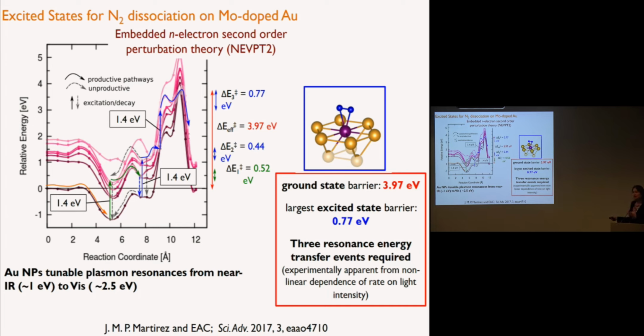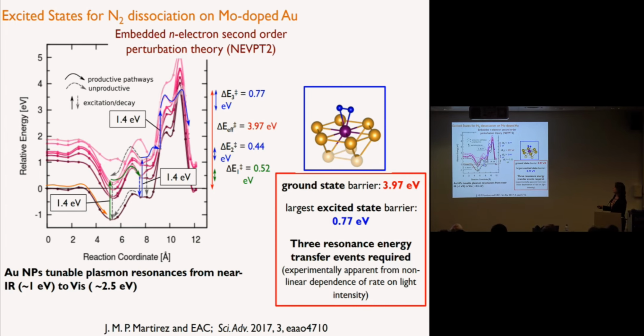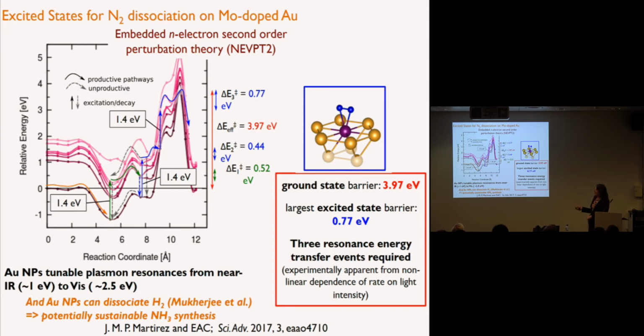And what our calculations, looking at these oscillator strengths, tell us, and the fact that we don't see charge transfer, is that this is happening through resonance energy transfer, and that's what would be needed in order to get this to happen. This got a lot of people excited. There are several experimental groups that are trying to see if this works. We certainly hope it will. You can think about then having a situation where you have these molybdenum-decorated gold nanoparticles that could both dissociate H2 and dissociate N2 and potentially lead to some sustainable ammonia synthesis. It's not going to happen tomorrow. Maybe it'll never happen, but it's proof of principle that it might happen.